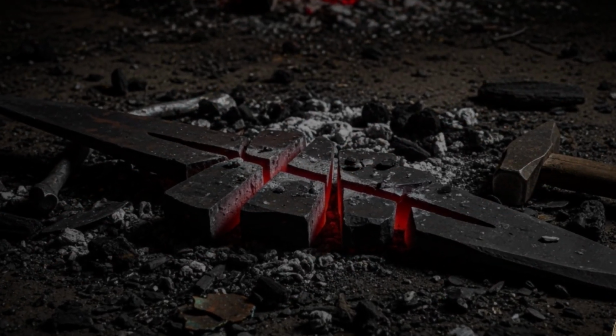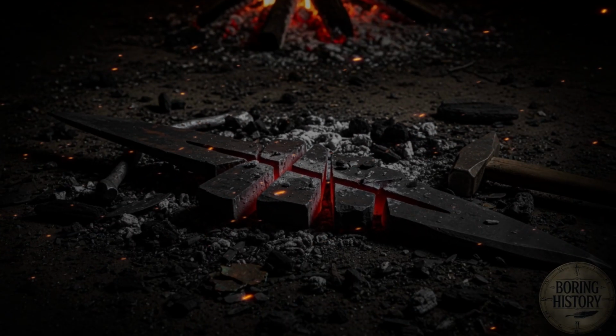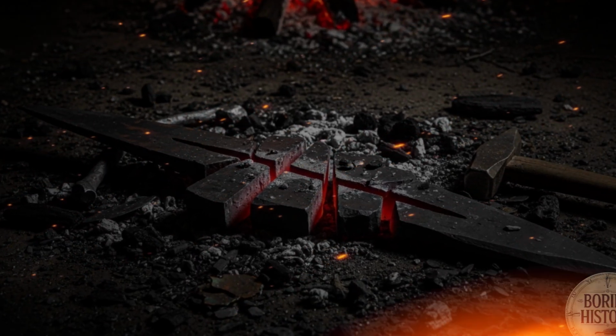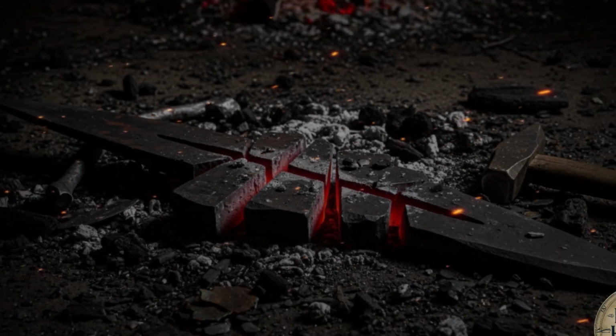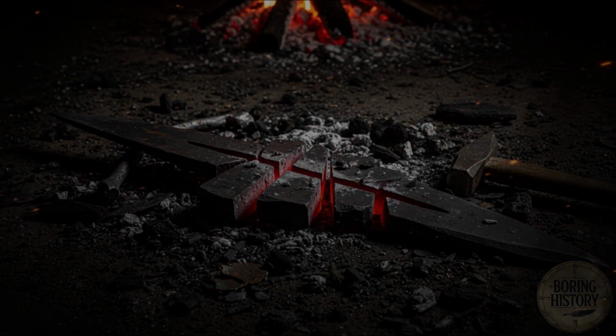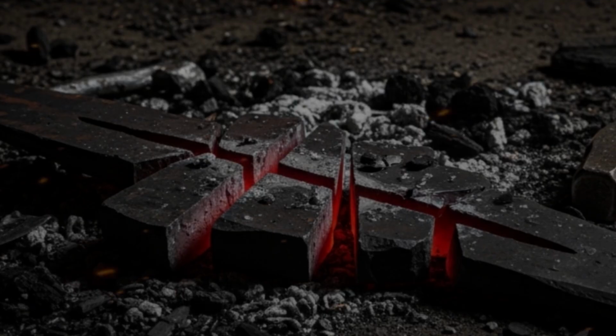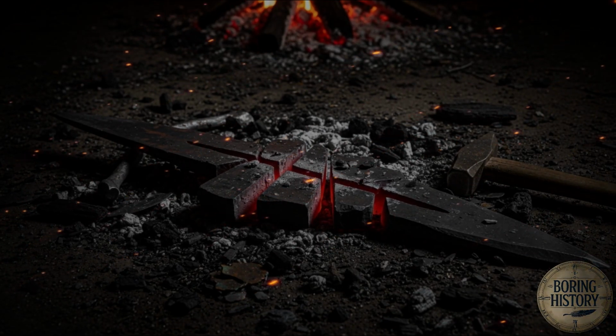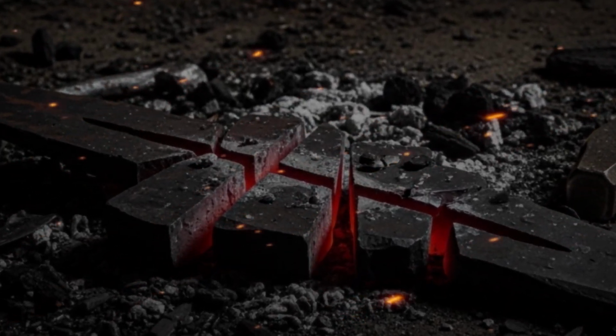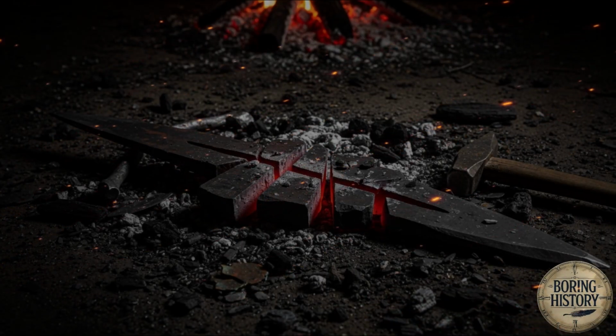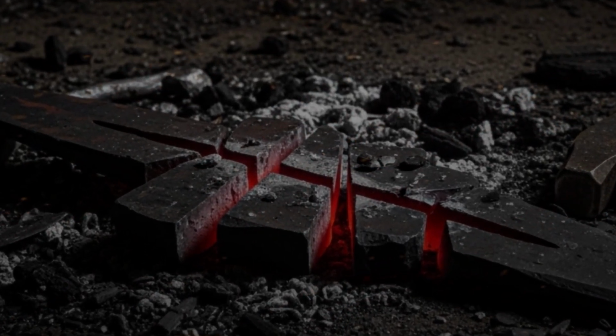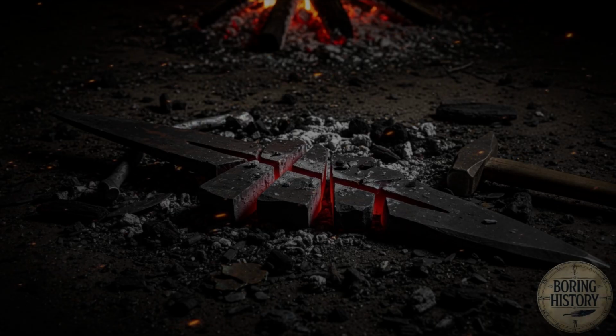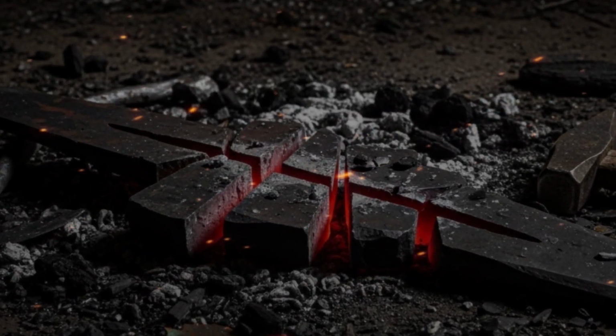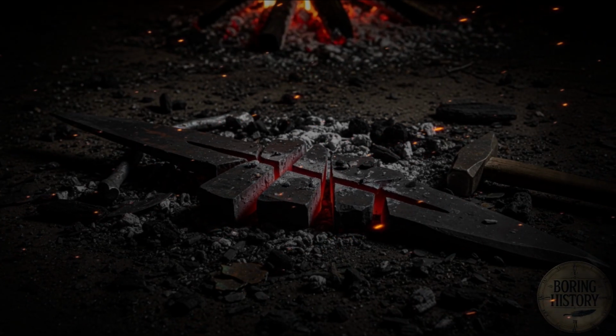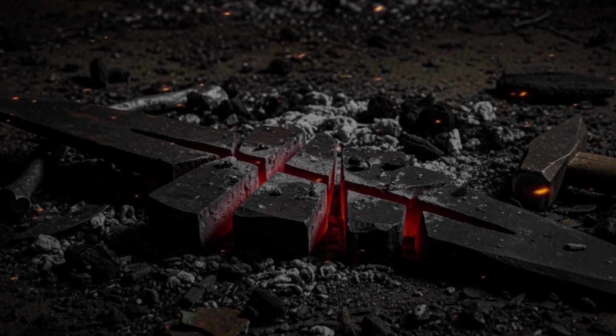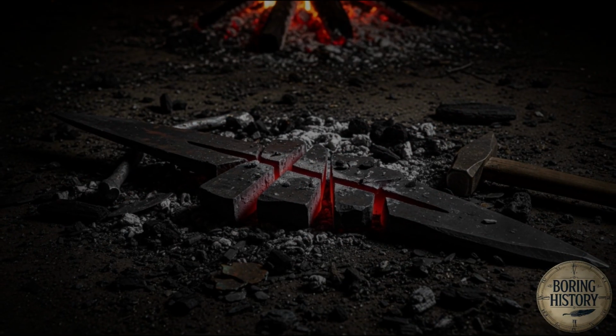The slag inclusions that bog iron always carried, those microscopic pockets of impurity distributed through the metal, behaved differently in extreme cold. In warmer conditions they were almost inert, their effect on the blade's performance subtle and gradual. But in deep cold, metal contracts, and as it contracts, the differences in contraction rates between pure iron and the slag inclusions created internal stresses. The blade became brittle at those points. A shock that would have been absorbed and dispersed in normal conditions instead cracked through the metal at its weakest places. Good enough became not enough.